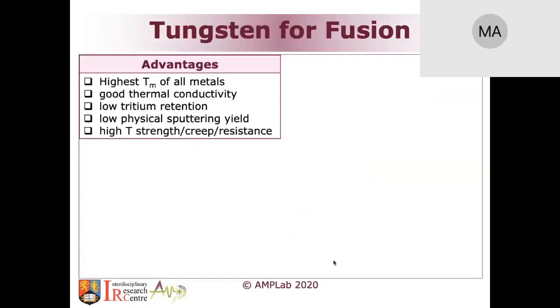So tungsten, what do you know about it? Tungsten in general has potentially the highest melting temperature of all metals that we know. It has in general good thermal conductivity. It has low tritium retention, which is an issue that we are worried about in nuclear fusion, because in that case we are using heavy hydrogen atom, tritium atom, essentially to combine and eventually form helium. And essentially it's a good material because it does not retain it inside it, which may embrittle it, in fact, later on. It also has a low physical sputtering yield and a good combination of high temperature strength, good creep resistance and good tensile strength.